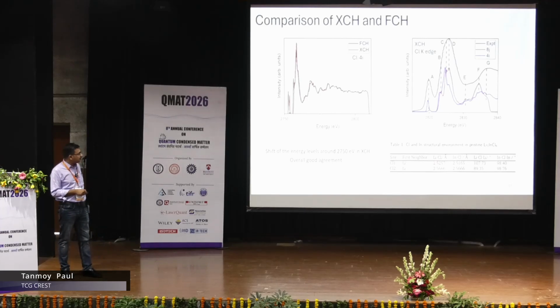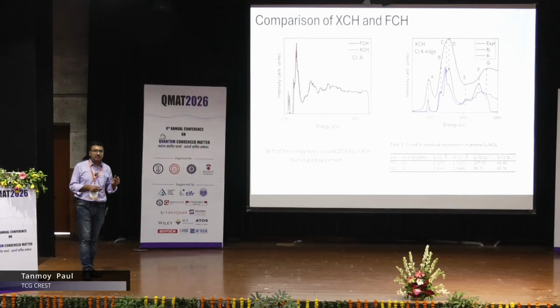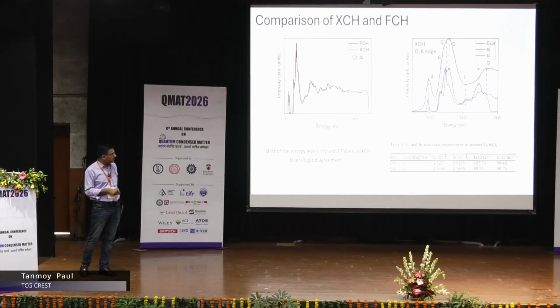To understand that, we look at the local structure. Although there are the 2 sites Cl1 and Cl2 that I have mentioned, their local environment is not the same. For example, Cl1 is bonded to lithium with bond lengths of 2.525 and then 2.566, but there is a bending of the next lithium, in the coordination. So we feel that this variation, especially in this regime, is coming because of this local change in the coordination number.